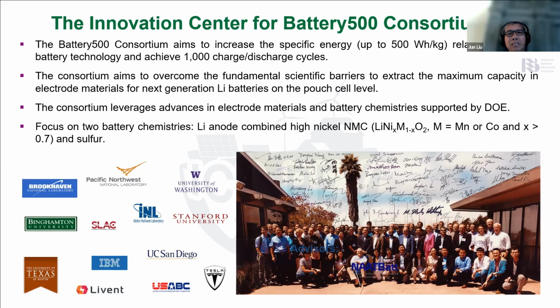The goal is to increase the energy density to 500 watt-hour per kg with more than 1,000 cycles. We have two battery chemistries we are studying: lithium metal anode with NMC, and lithium sulfur. What's fundamentally different for this program is that we are not only doing battery materials research. We develop the best battery materials and electrolytes, and then we put them into the best designed real batteries, real pouch cells, manufacture the pouch cells, and demonstrate and validate the performance. If it doesn't work, we try to find out what's wrong on the whole cell level, and then what's the approach to improve it.